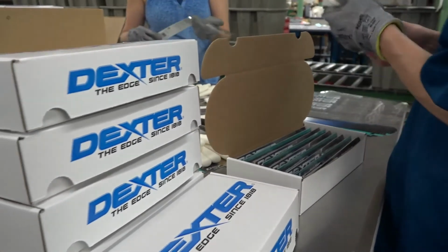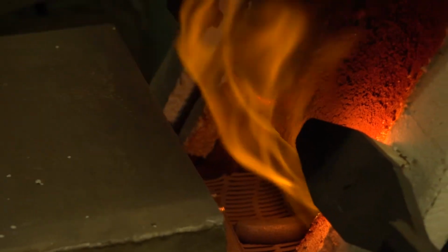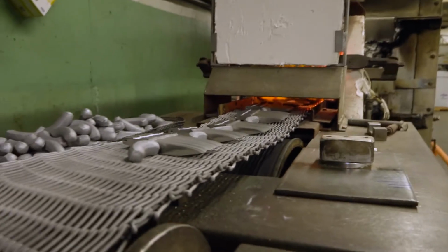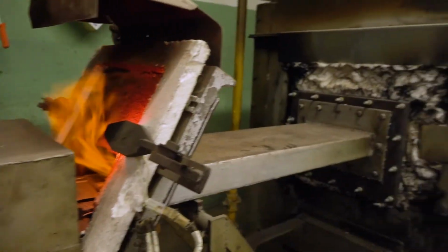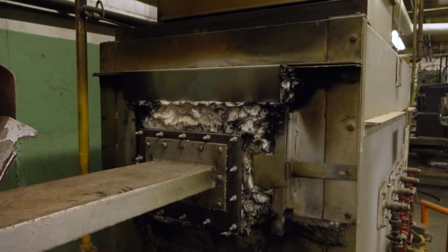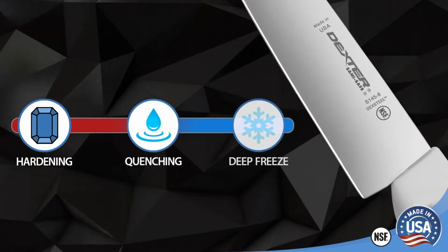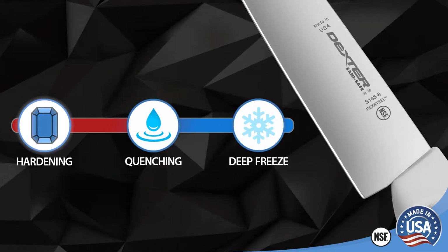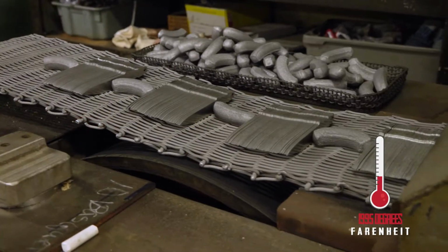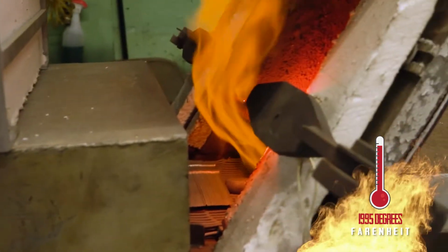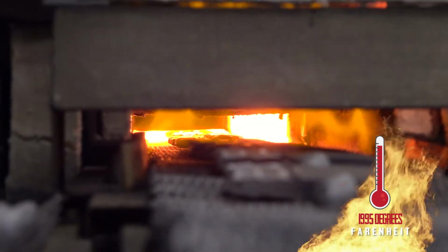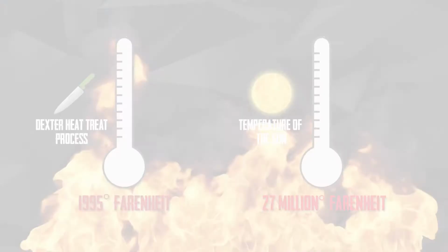You could put the best package on the knife, the best handle, use the best steel, polish it pretty, but if your heat treat isn't correct, none of that matters, because that's where the heart of the knife is. There's a few parts to heat treating. The first part is the hardening process. The initial hardening process, we are slowly heating those blades up to 1,995 degrees Fahrenheit. Is that the temperature? That's the temperature. Pretty close, though.